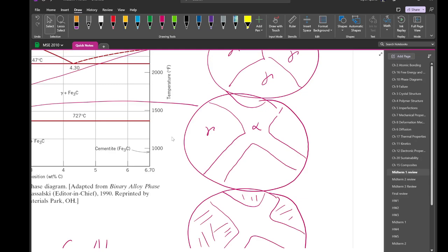Look at the second image. Why are there dashes in the S line? In the second image, we're in a two-phase region now, where the original phase was austenite, and we started to form a secondary phase. So we have options on where it's going to go, along the grain boundary, or precipitating in the middle. It's going to be lower energy to form along the grain boundaries, because if this is the grain boundary, this already costs energy. So why would I create a new boundary in the middle of pristine lattice if I can just put it there? The only reason is that it takes diffusion to get to the boundary. If you don't have that diffusion, it's not global enough, and you have to hold it in the middle of the grain. So what gives this thing diffusion there if it doesn't have layers?